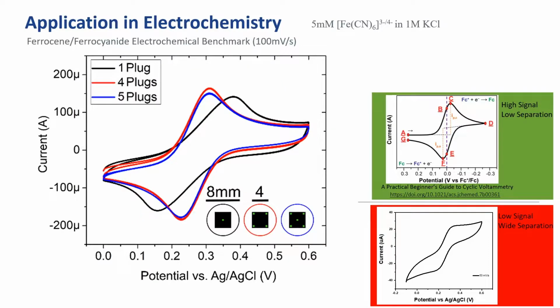Similarly, we vary the number of plugs present within the same footprint of laser-induced graphene material. There is a marked decrease in the peak separation from one plug to 4, after which an additional plug only serves to reduce the active area of the electrode. This suggests that reducing the contact resistance is necessary to achieve high-quality results, but this contact resistance need only be low relative to the sheet resistance of the laser-induced graphene.